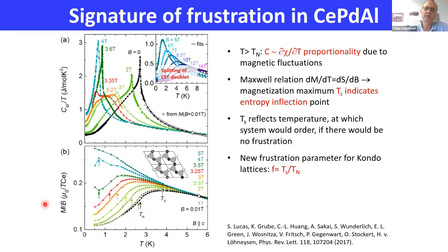Now, more recently, we were asking ourselves how we can actually define magnetic frustration in such metallic heavy fermion systems, because the ordinary frustration parameter which experimentalists use for insulating frustrated magnets won't work. There we typically define as a frustration parameter F the ratio of the Curie-Weiss temperature divided by the actual ordering temperature. And the Curie-Weiss temperature in insulating frustrated magnets gives us the energy scale of the dominating magnetic exchange. But in the case of a Kondo material, the Kondo scattering already leads to a modification of the temperature dependence of the magnetic susceptibility, and the Curie-Weiss temperature is often just a measure of Kondo decay, and it has nothing to do with the magnetic intersite interaction. So it's not suitable to define some magnetic frustration.